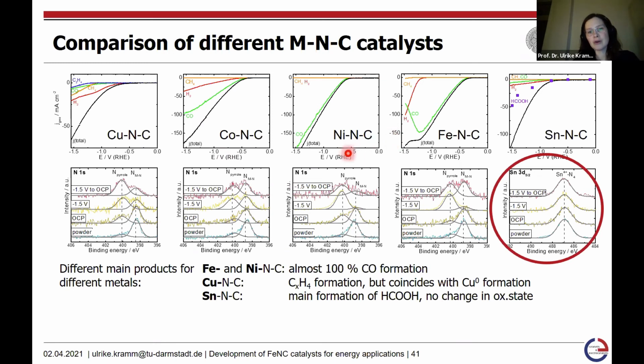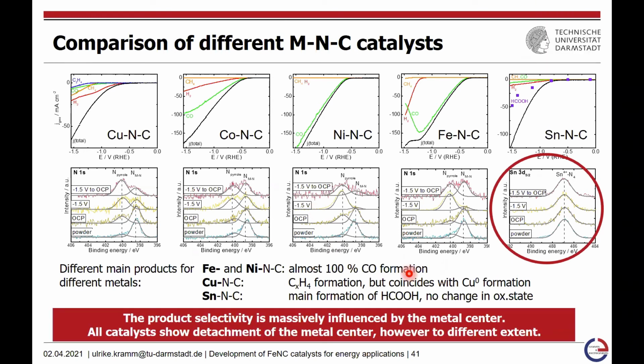But in almost all cases, we were able to see that the metal center gets disintegrated at a potential of -1.5. In the next step, we will also investigate some further potentials, basically to identify the stability window for the molecular type of active sites, as so far it seems that it might be more the metallic state which is responsible for the different catalytic reactions.